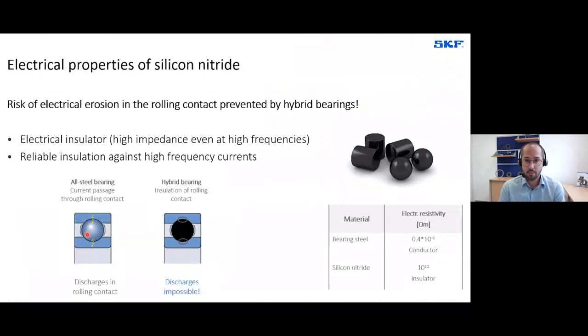If you use hybrid bearings with ceramic rolling elements, this cannot happen anymore. Ceramic material and silicon nitride is an insulator, and it is an insulator between the two rings in the range of several millimeters. So even at very high frequency currents, there is no risk of electrical erosion if hybrid bearings are used. So if you have inverter driven machines with very demanding bearing currents, hybrid bearings are the most reliable solution to avoid any issues of electrical erosion or early bearing failures due to it.